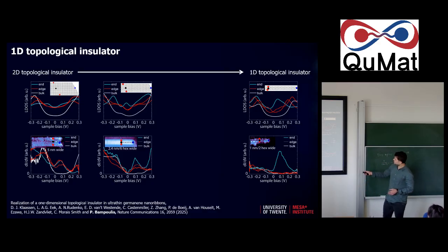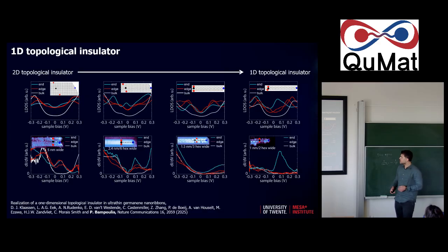Now you might ask what's happening in between these two ribbons, between 6 and 2 hexagons. A lot of things are happening. There's a complex behavior. You get something similar to what people have observed in the graphene nanoribbon, where you have an even-odd effect as you go from an even number of hexagons to an odd number of hexagons. For example, in the armchair graphene nanoribbon, you open a gap, you close the gap, you open the gap, you close the gap, and so on. So you get this even-odd effect.